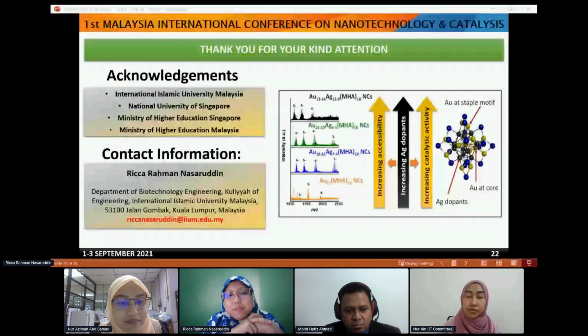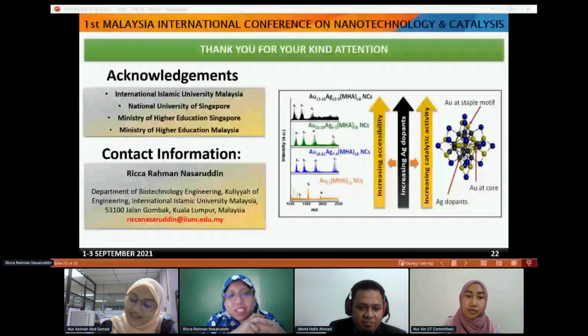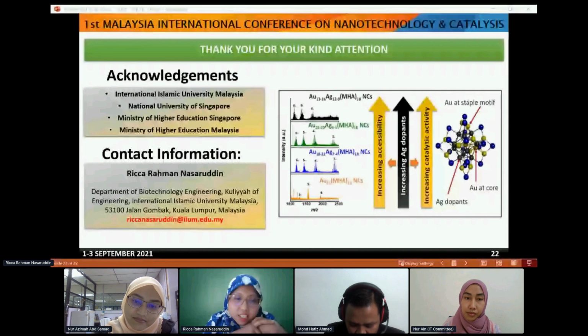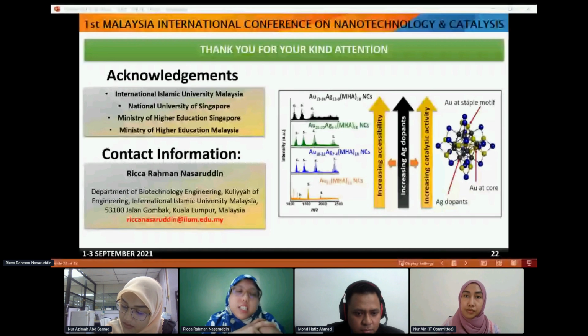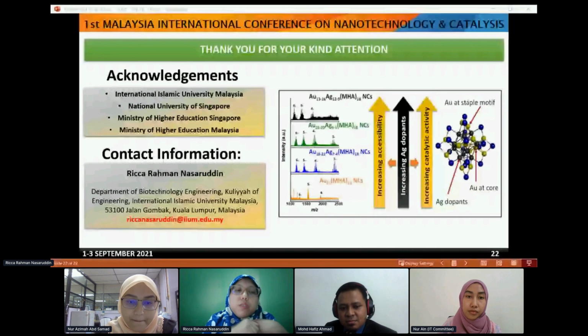Is it possible if I combine this material with, for example, my zinc oxide or titanium oxide? Yes. Usually what we do, it is as an electron mediator. It will give some enhancement, like a photosensitizer. In cancer therapy, we use gold nanocluster as photosensitizer. It can mediate the transfer of electrons because it is small, so you can just decorate your catalyst with this one. Okay, thank you so much, Doctor.